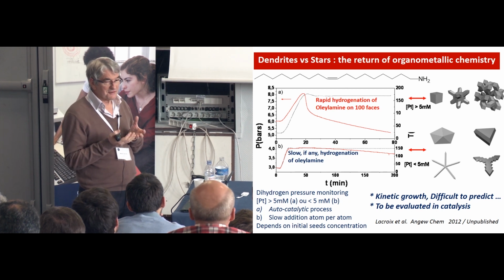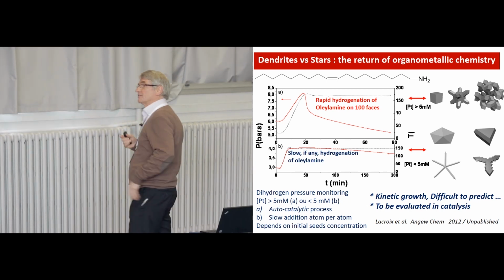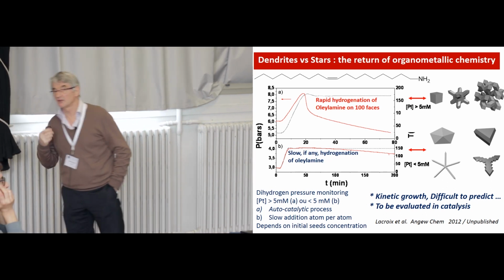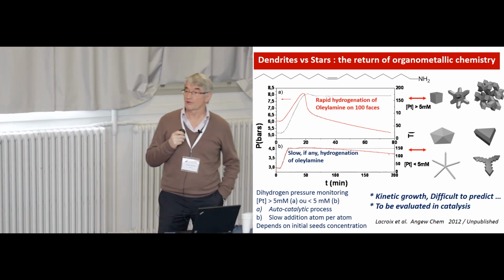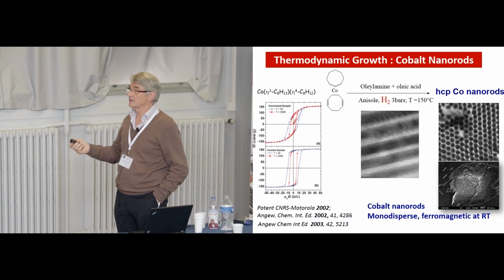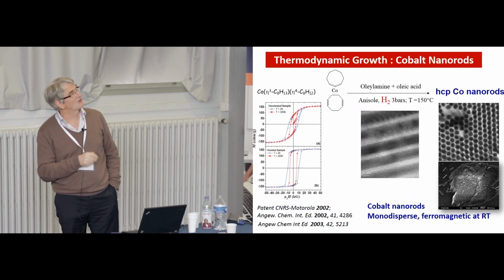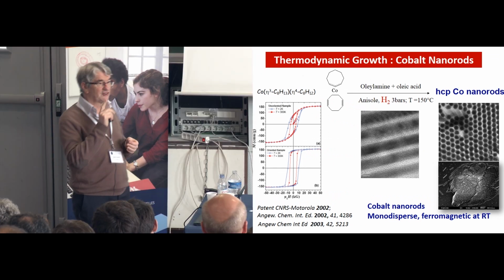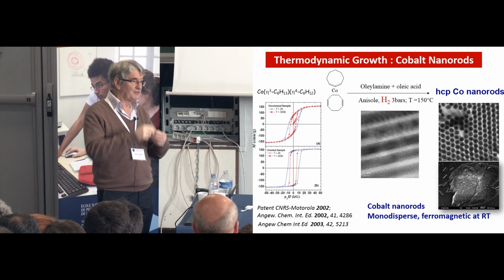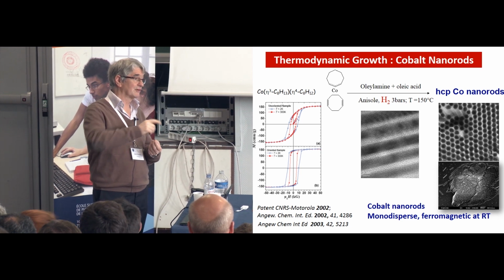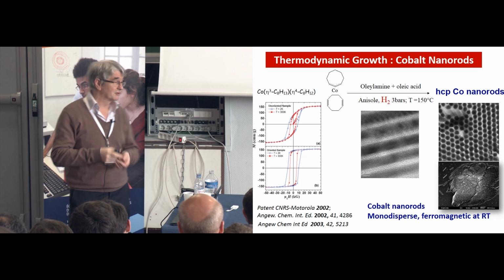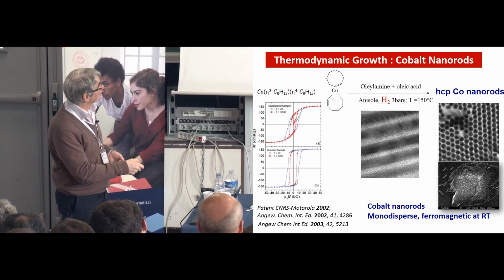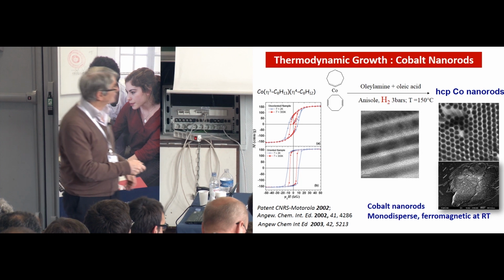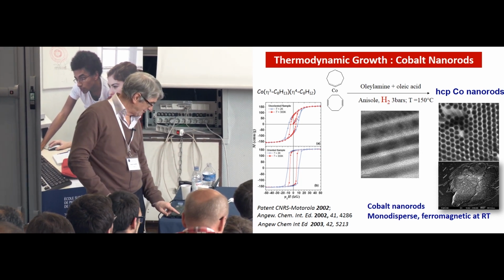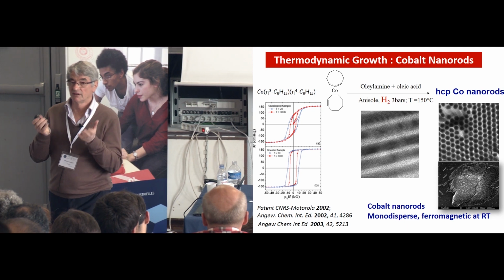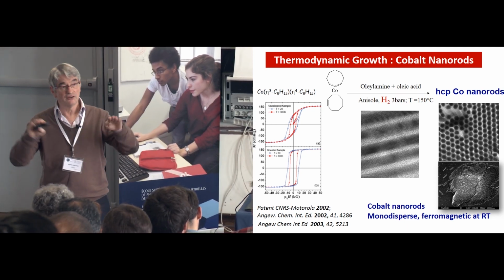Then thermodynamic growth. Somebody asked, can you predict what will happen when you decompose? Yes, you can predict, especially after the reaction. And it's what happened with cobalt, because cobalt is HCP, and if you grow single crystals of cobalt, you have a preferred axis of growth, and you will make cobalt nanorods, which are monodispersed in diameter and size. If you go to iron, which is BCC, you expect cubes.